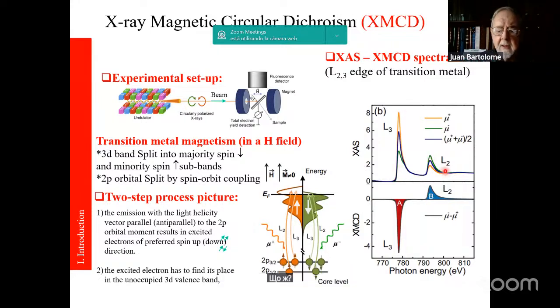The first process, the L3, as we scan through the photon energy, will show as a peak around the edge value. And in the second case, with the left circularly polarized light, it shows as a lower peak. The difference between the two peaks is precisely the XMCD signal, in this case for the L3 edge. Of course, we do the same in the energy region corresponding to the L2 excitations, and we see again in the absorption two peaks, although reversed in magnitude. So in this case, the difference is positive. The average between the two is the absorption. So this is the basics of the XMCD experiment at the L2,3 edge.